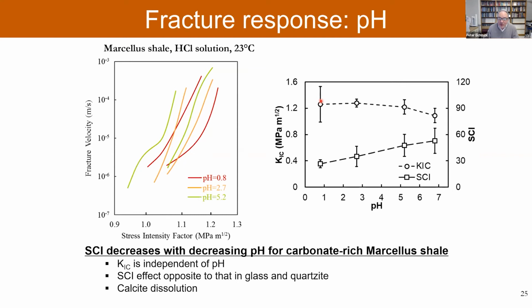Why is this different for the fracture toughness from the subcritical index? Well, remember, this describes the rapid fracture growth, and this describes the slow fracture growth behavior. There is more time for the slow fracture growth for the water to interact with the rock. So there's more time for the chemical assistance to fracture growth. So this affects the subcritical index, whereas it doesn't affect the quick fracture growth in the critical fracture growth. So this is for the carbonate-rich shale. I'm not showing it to you here, but the clay-rich shales that have very little carbonate, we don't see this effect.